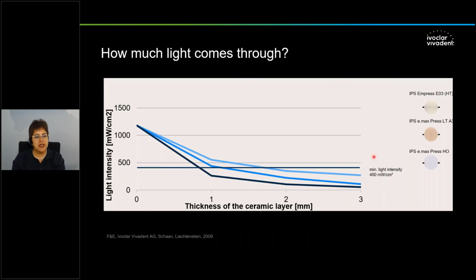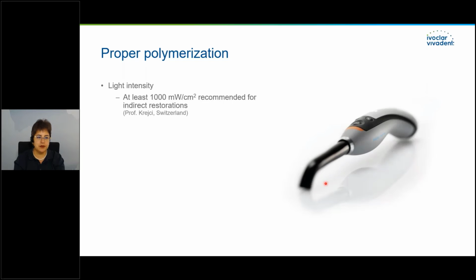You see that for the HO, you always need a dual cure luting cement, otherwise it will not be possible. And we say until 2 millimeters, you can use light curing cements with high translucent materials for veneers. But after the 2 millimeters, we will always need a dual cure cement.